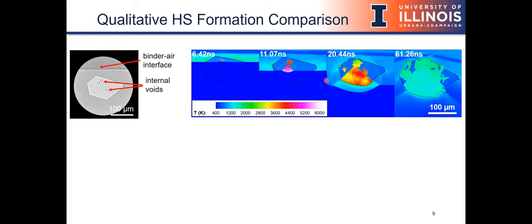In that configuration, we're viewing from the bottom. So it's like the shock is starting from behind the screen of the computer and coming out towards you. Even though these geometries are a little different, as you'll see, we can still compare. Here I'm showing some results. On the left, we have the cross section that we ended up going with. We also see it had a significant amount of internal voids. On the right, we have the simulated temperature maps that Chauvin generated. In this first tile that was around 6 nanoseconds, we see that the shock front, which is this line here, has traveled through the top of the crystal. There has already been the collapse of some internal voids. If you zoom in, you can see the temperatures are around 6000 Kelvin max.